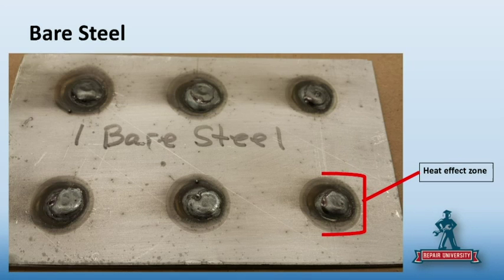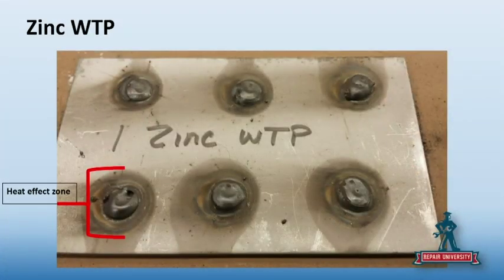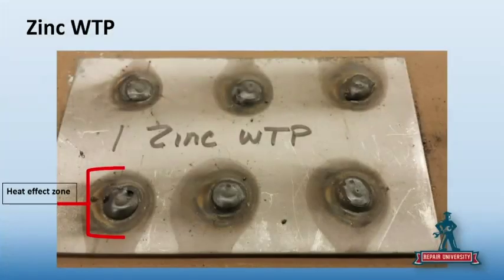Now you've got a zinc weld-through primer in the zone that you're welding through. And you can see, again, because you get a poor first initial strike, that you've got to spend more time in the weld zone, so you're getting a larger heat effect zone. And look at the inconsistency, even with the heat effect zone, as you weld these together versus the other ones, which are welded very close together. This is being welded, and you can see the resonation as it goes on. The area gets bigger and bigger because that heat's carrying more because you have another product in there that's being conductive of the heat. Right, and you're starting to see the weld nuggets aren't as nice, they're taller, there's not as good penetration, and the one that's pictured has a little porous crater in it.